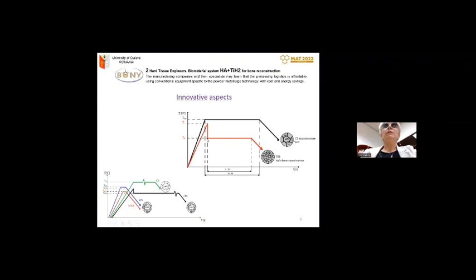So finally, from these three new sintering techniques we decided to select two-step sintering, because it is done in a conventional sintering furnace. As you know, spark plasma sintering is a very developed technology with special tools, which are quite expensive. With microwave sintering, we have some problems controlling the temperature. So we said, let's try this two-step sintering. And we obtained quite beautiful results.